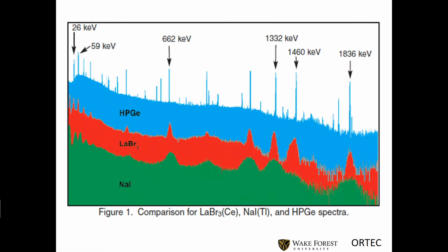And this one basically is because of the perfection, and it's also the statistics. These operate according to Poisson statistics, and these being actual charge carrier collection have different statistics, and that contributes too. But it's mainly these being such perfect materials. You produce the electron hole pairs, and you manage to collect pretty much every one of them, and that's what's not giving that non-proportionality. Whereas down here there are lots of things going on.